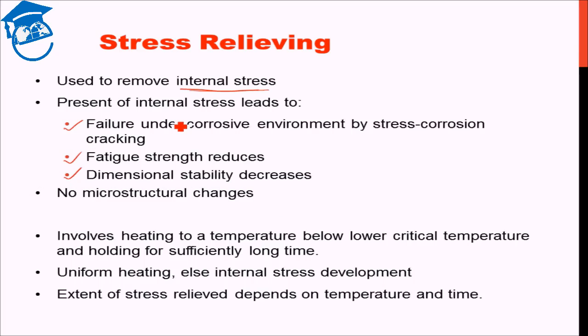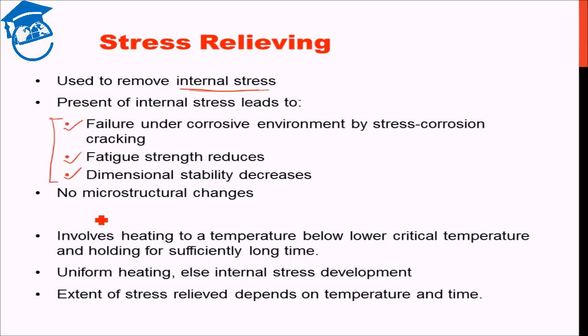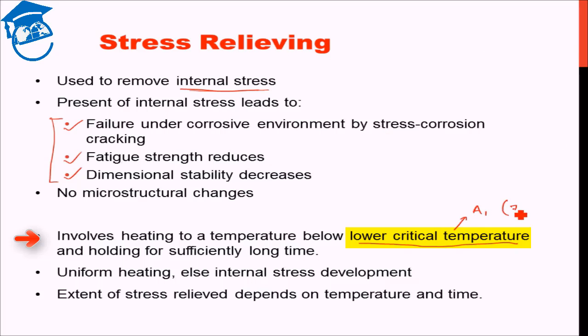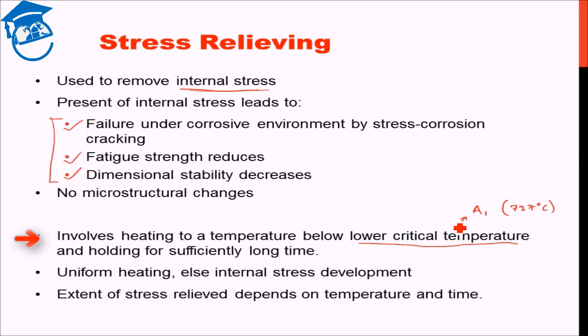The process of stress relieving, which leads to removal of internal stresses, helps us counter these problems. During stress relieving there is no microstructural change observable under a microscope. What we do is heat the body which is under internal stress to a temperature below the lower critical temperature — that is, below the A1 temperature at 727 degrees Celsius — and hold it for a sufficiently long time so that the internal stresses relieve themselves.